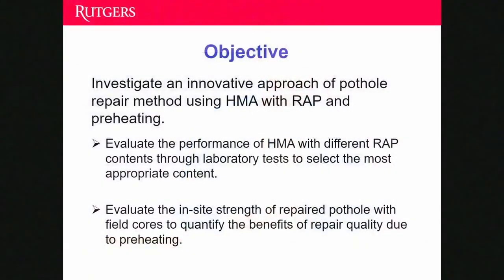So this study includes two parts. The first part is to evaluate the performance of HMA with different RAP content through laboratory experiments. Then we will select the most appropriate content and add it to the new HMA as the patching material for field evaluation. The second part is to evaluate the in situ strength of the repaired pothole with the field cores, and then we quantify the benefits of this repair quality.